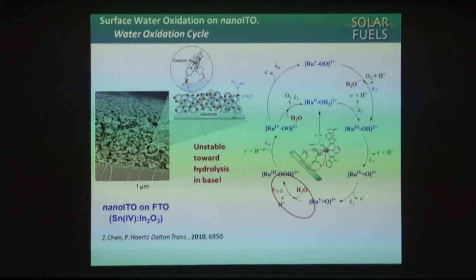But let me go back here at the end and finish the story about water splitting. Here is, again, one of these catalysts. This is, again, that favorite carbene catalyst. I'll still use it again, but now instead of having a bipyridine as one of the ligands, I've gone back and done the synthetic chemistry to have phosphonates. That means that everything I did in solution can now be translated to an oxide surface. So that's great. I want to have a device, I have to have things on surfaces. I have to have an interface.